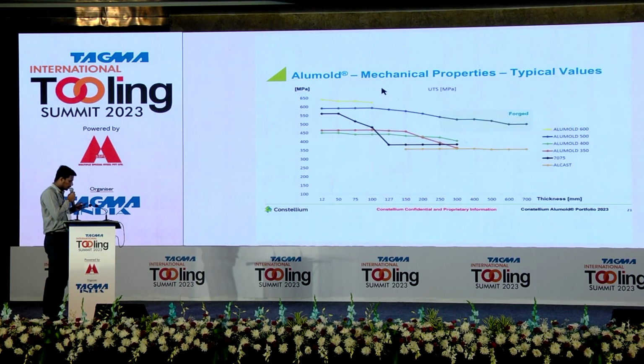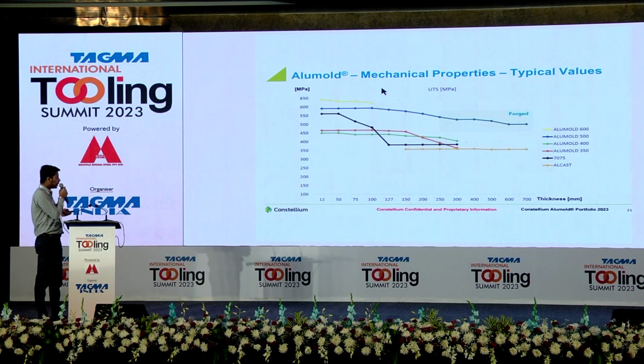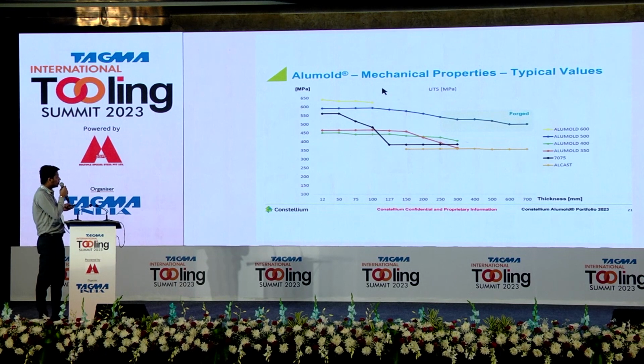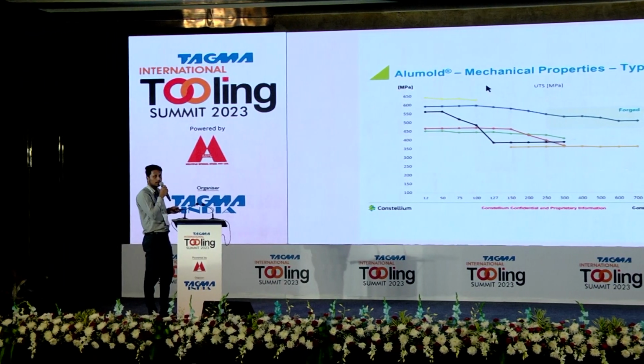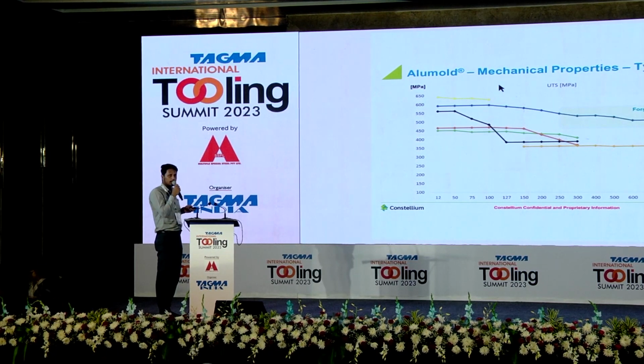Yeah. As I told, Ms. Susan Tan has specifically spoken to me regarding the 7 series alloy. Alumold 500 is developed from 7075 itself. But the major disadvantage of 7075, when we go to deeper machining conditions, or when we increase the thickness and do more pocketing, is that the mechanical properties reduce drastically. The black line indicates traditional 7075, whereas the blue line indicates Alumold 500, where the mechanical properties don't change much when increasing the thickness. So the material properties homogeneity is fantastic.